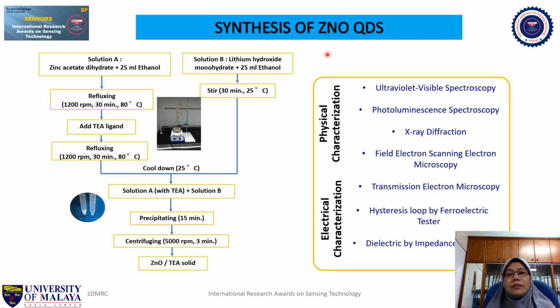Zinc oxide quantum dot is synthesized by following this flowchart. We initially use two solutions, solution A and solution B. Solution A will be refluxed, then added with TEA ligand, and refluxed again before cooling down to 25 degrees. After that, solution B will be added to solution A, and the solution is precipitated for 15 minutes and centrifuged at 5000 RPM for 3 minutes, and finally we obtain zinc oxide quantum dot with TEA